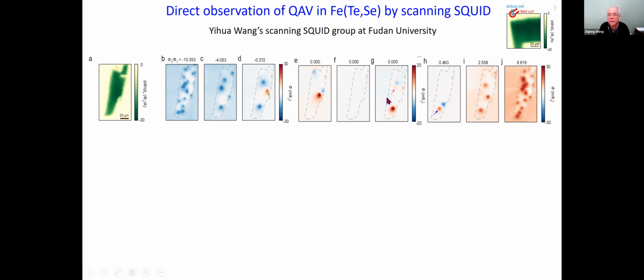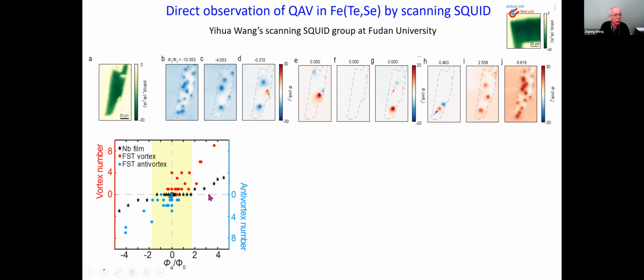And it's actually a stochastic phenomenon because at different times, you might nucleate these things at different iron impurities. And if you do this in a field, of course, you have vortex or anomalous vortex. Now, this phenomenon is not seen if you use FeSe. It's also not seen if you use niobium, a standard BCS superconductor, which they actually showed in this wonderful plot. If you first look at the stars, which is from a niobium film, when you have no applied field or small applied field, you have no vortices. Right? You need a threshold, Hc1, to actually see these things coming in for niobium.